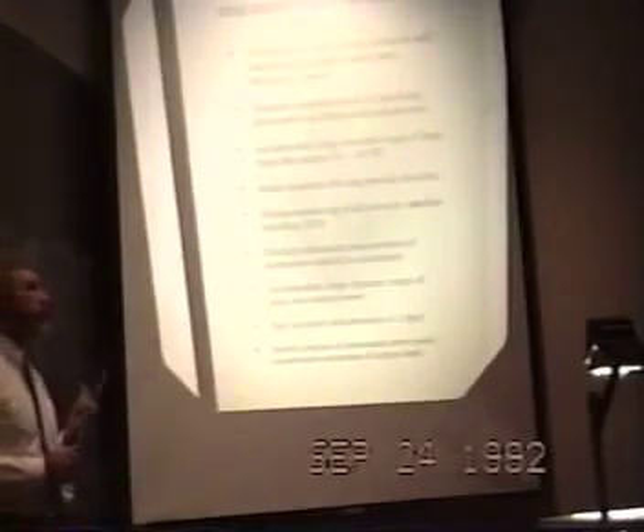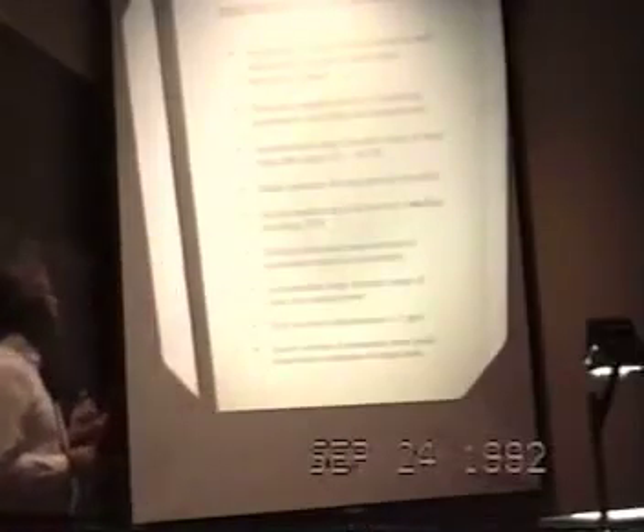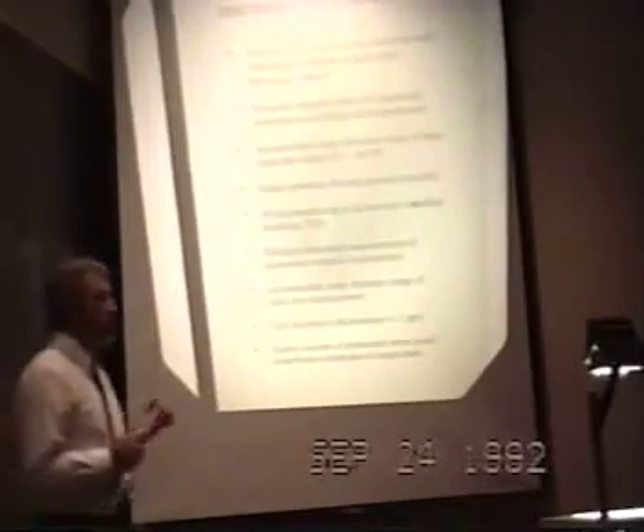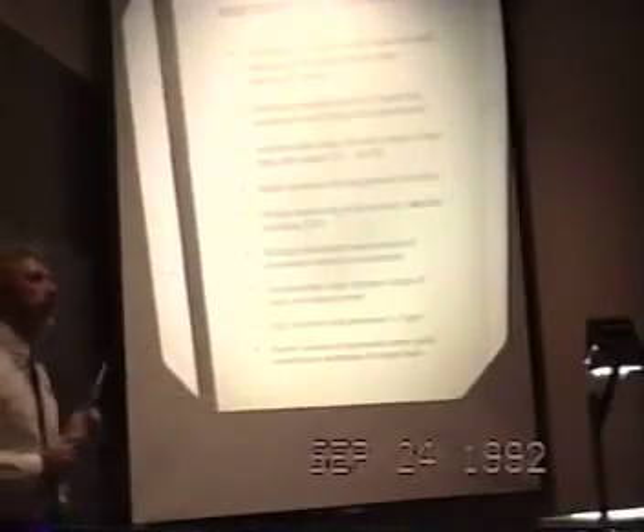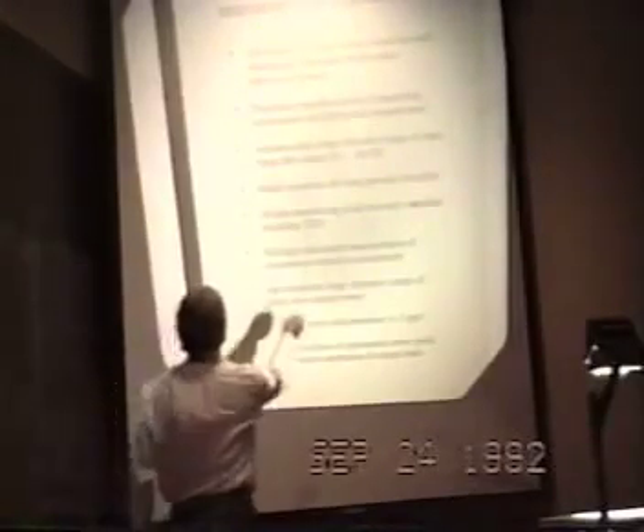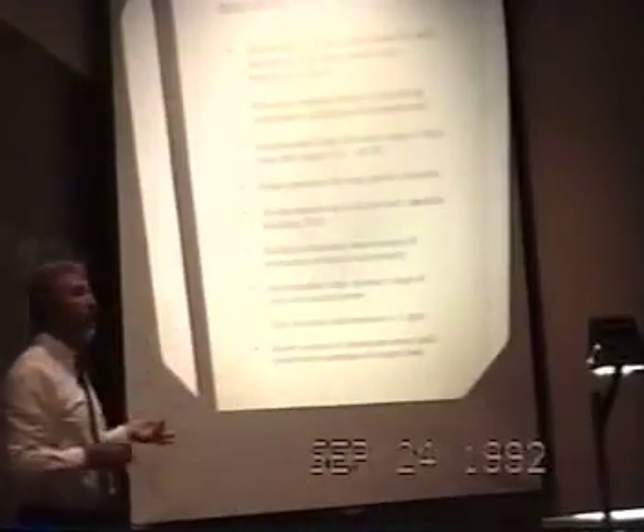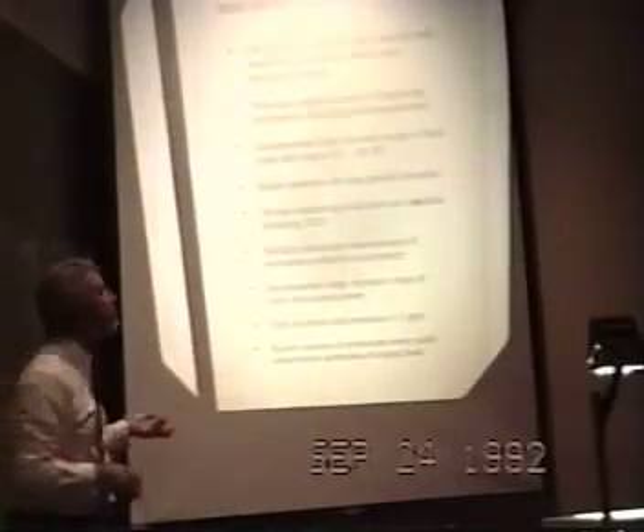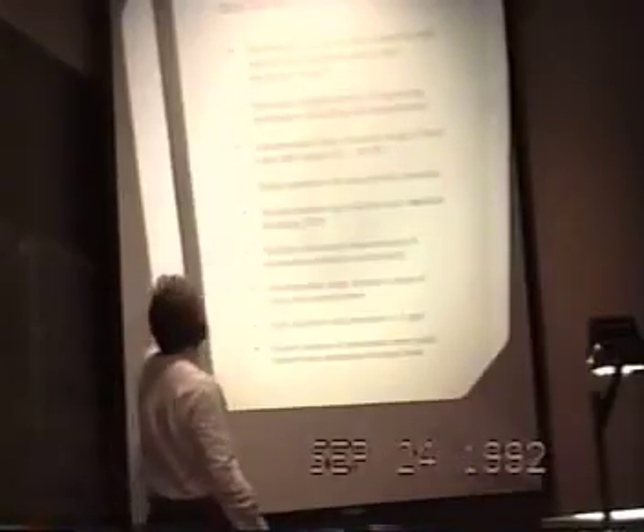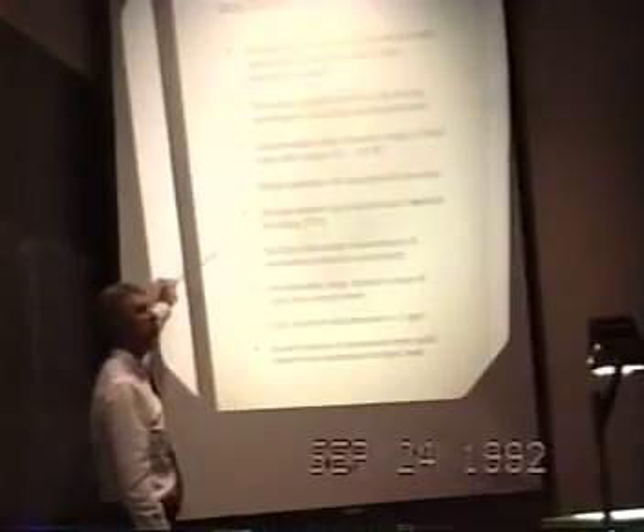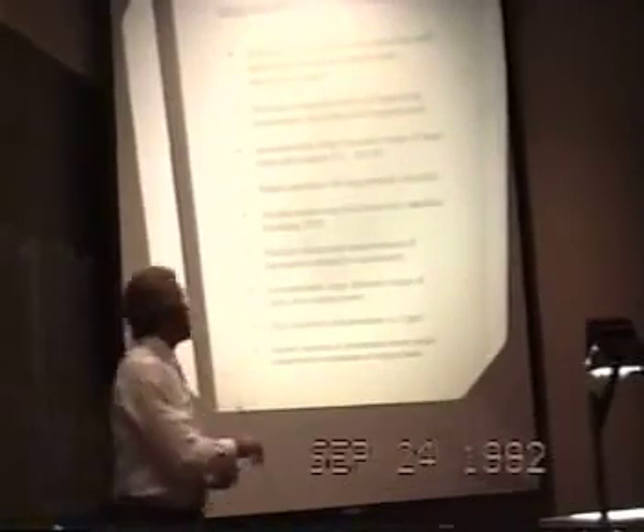We wanted to maintain complete control of the operating parameters, where one of the operating parameters of an electrochemical system is the cell temperature. We felt that we needed to accommodate a very large dynamic range of the heat input and output, a range in the calorimeter from 1/10 of a watt to 100 watts, stable operation for months, online monitoring of all of the relevant variables, including the deuterium to palladium ratio, which we believe to be important in